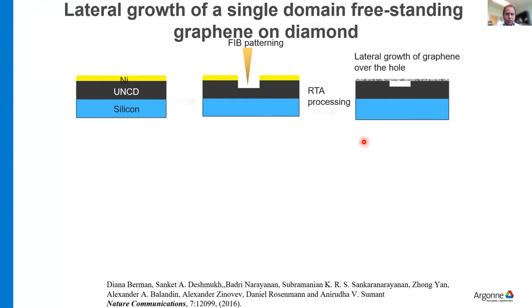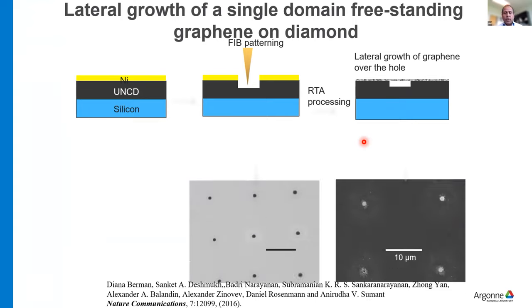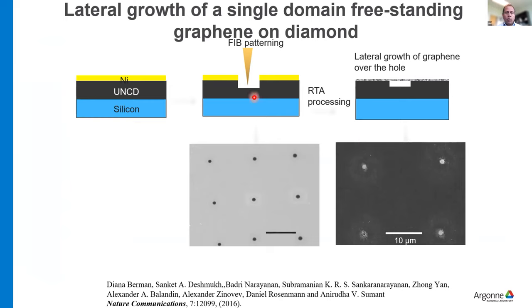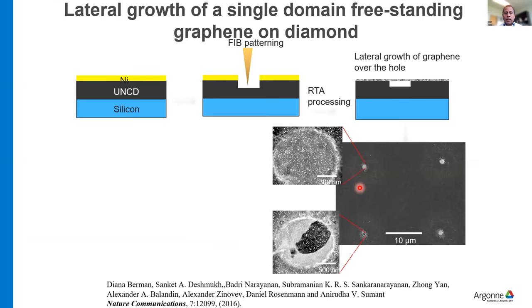Now, since we got excited about this process, we wanted to further see exactly how the mechanism of this graphene growth happens. So we did an interesting experiment. We actually made a hole with the FIB before the RTA processing, rapid thermal annealing. And then, after that we did the annealing. So as you can see, this is before and after the annealing process. The holes are basically covered now with the graphene. So within a minute, it covers that hole, and then we get a nice graphene already grown over the hole.